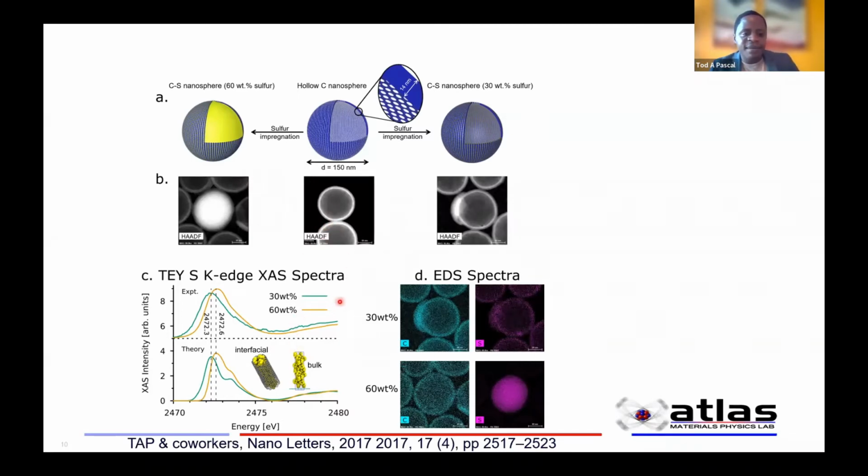So we figured, well, all right, it works for lithium salts. Maybe we can start looking at some more interesting systems. And this system was particularly interesting for us because we were interested in lithium sulfur batteries, which have incredible promise, but have for a long time been held back by the fact that during cycling, we get these short chain lithium sulfur species that are typically soluble in our electrolyte. And so our cathode material starts degrading over time. We're typically only able to get a few cycles out of this battery before it dies.